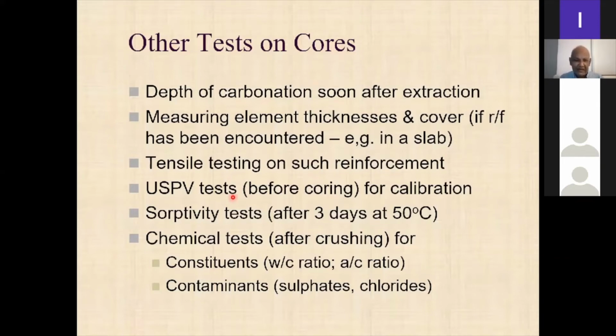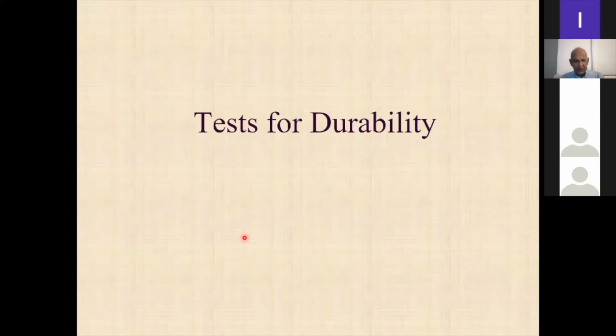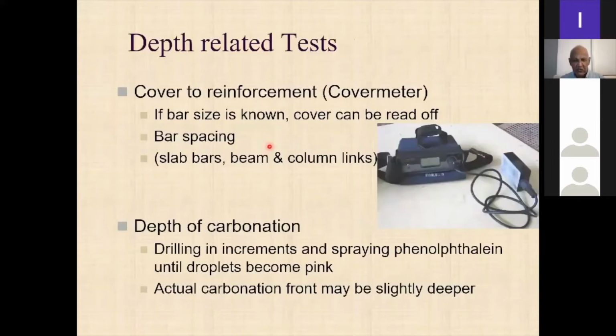And there are these other tests also that can be done, right? So these are some tests for durability. I'm going to skip the ones that have no direct influence on in situ testing, right? But say cover to reinforcement, very important, right? In addition to information about durability, it will also tell you something about the lever arm of the slab. And also the cover meter can be used to locate where the reinforcing bars are, right? Because once again, if you remember that first slide that I showed about that moment of resistance ratio, in fact, the bar diameter and the bar spacing have a big effect on the moment of resistance.